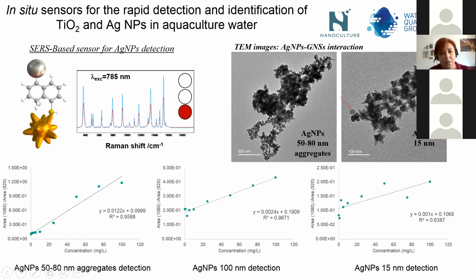This will be enhanced by the presence of the plasmonic particles, and further enhanced by the presence of silver nanoparticles that are plasmonic as well. What you can see here is the spectra that we will get, and the increased intensity of the spectra when we have silver nanoparticles. What you can see here is that effectively we could check in electron microscopy the interaction between the gold nanostars and the silver nanoparticles.